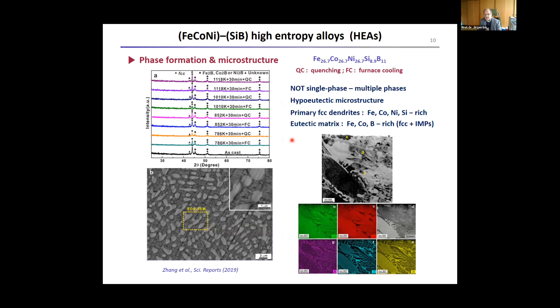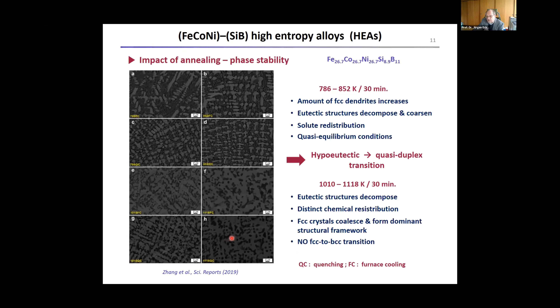Here is now an iron-based system. If you make the composition relatively complex, you have in this case not a single-phase material, but an FCC structure coexisting with some intermetallic phases — a characteristic microstructure. If you look deeper and think about higher-temperature stability — by doing some annealing treatment — you see that there are phase transformations: the amount of FCC dendrites increases upon annealing, the eutectic structures may decompose and coarsen, and there may be redistribution of solute elements, sometimes segregating to grain boundaries.